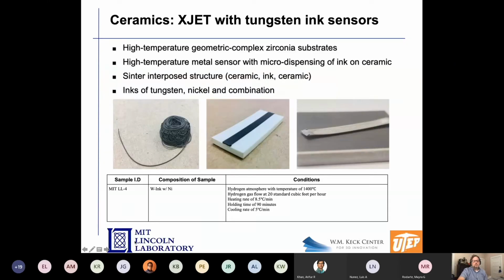And so another project with MIT Lincoln Labs is they have these inks that are tungsten and nickel, or a combination. And tungsten has a melting point of like 3600 C. So we're trying to do this overmolding idea that I just mentioned in polymers. We're trying to do it with ceramics now, where we can make 2 parts that have some sort of complex mating surface, and we can put the MIT inks into them, and then we fire them. Basically the ceramics consolidate. The tungsten might melt to some degree, particularly if we alloy it more with nickel, and we could get conductive materials inside of dielectric materials.